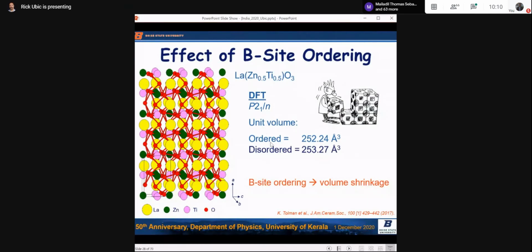We did DFT, and we did prove it, that the ordered form, in this case we used the lanthanum zinc titanate compound, which orders. We simulated an ordered and disordered form, and the disordered form has a larger volume than the ordered form. So it's true, B-site ordering involves a volume shrinkage, and that shouldn't come as a big surprise, and we just quantified it.